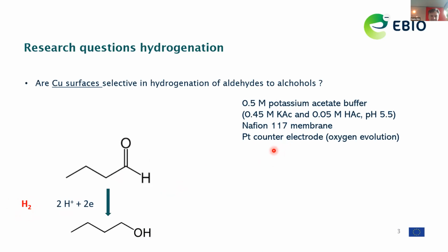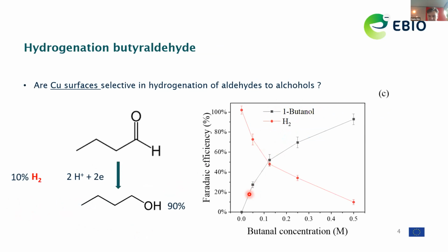So what is the result of the first reaction that we looked at? The butyraldehyde hydrogenation that you can see over here depends very strongly on the concentration in the buffered solution that we added. So here you see from 0.0, so nothing, to 0.5 molar of butanal. And what you can clearly see is that the higher the concentration of the butanal is, the better the efficiency is towards the butanol. And at the same time, we suppress the formation of hydrogen if we go to higher concentrations. So the conclusion here is that it does work, and in the highest concentration, up to 90% alcohol is formed and only 10% hydrogen. But indeed, you need a significant concentration of the aldehyde to reach these high Faraday efficiencies towards the formation of the alcohol.